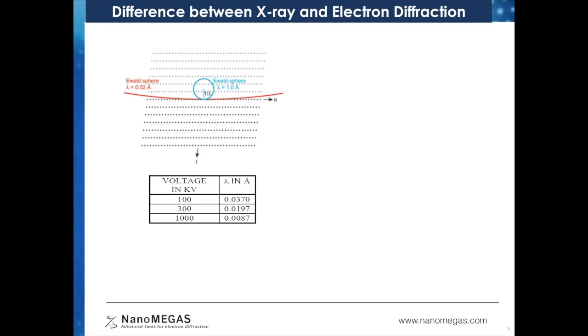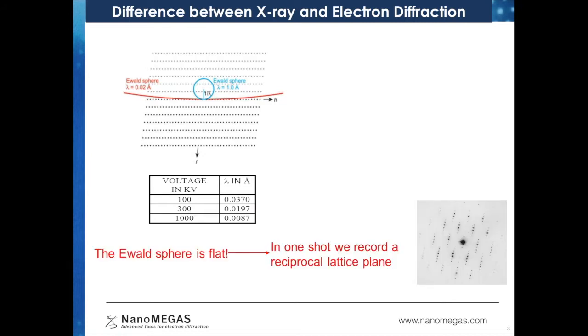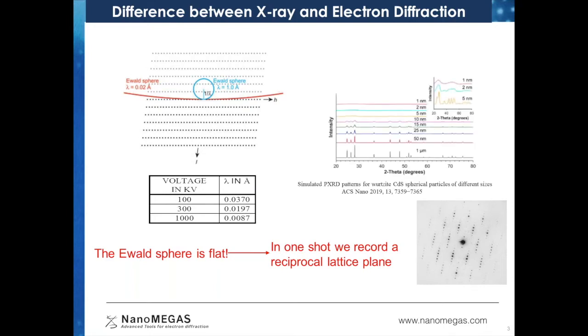Now, what are the major differences between X-ray and electron diffraction? As you can see, for electron diffraction, the Ewald sphere is flat in comparison to X-ray, because of the very short wavelength used in electron diffraction. That means one can collect sections of the reciprocal space in just a single shot. Also, we know once the crystal size becomes smaller, the diffraction pattern becomes very broad. As you can see in this example, with crystal size smaller than 10 nanometers, the diffraction pattern is extremely broad. It is known as X-ray amorphous, but this size of crystals we can study in a TEM to obtain suitable structural information.